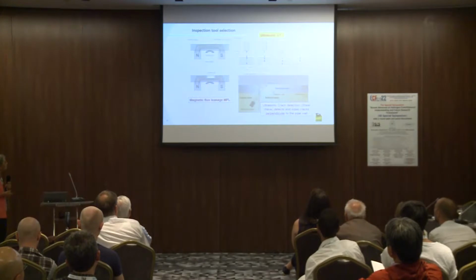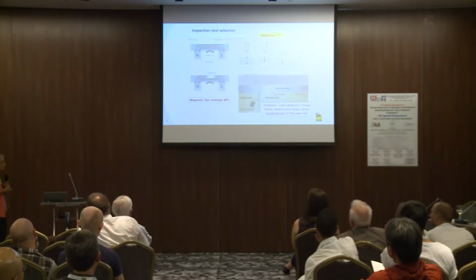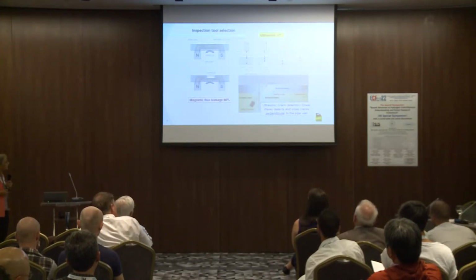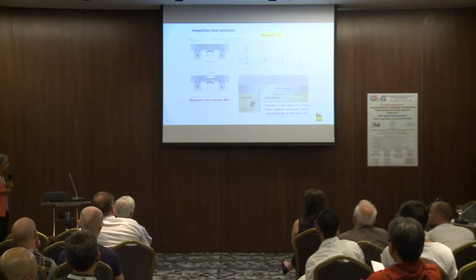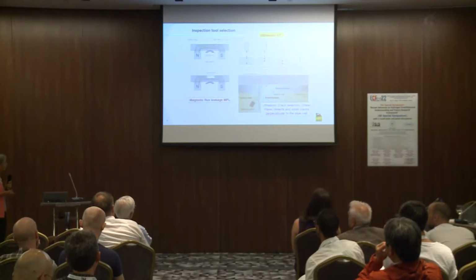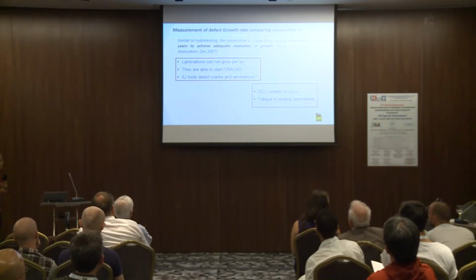In this case, for instance, at the beginning we used this pig, which is a magnetic pig, and this one sees very well the reduction in thickness, but doesn't see cracks. Instead, if we use ultrasonic, we can see cracks, but we cannot see very well the reduction in the wall thickness. So the point is that at the same time, the idea was, are those defects going to grow?